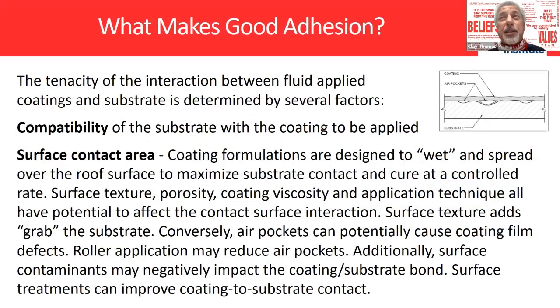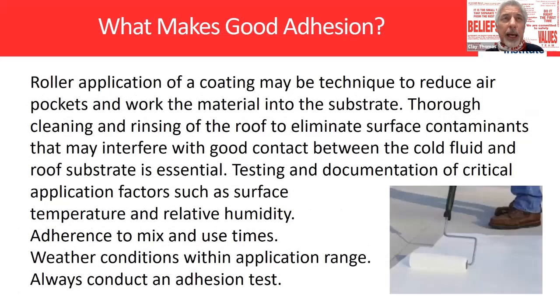And adhesion has a lot to do with a lot of things: the compatibility of the substrate to the coating, the surface contact area. And when I say compatibility, I could mean the fact that that surface wasn't cured or dried enough, that the substrate we're putting it on has a moisture content that is too high. You're looking at problems with your coating application. And we'll talk a little bit more about that because we have a project right now that we're learning on, for lack of a better term, because every project tends to be different and have its own unique challenges. So, are you talking about the GSA building?